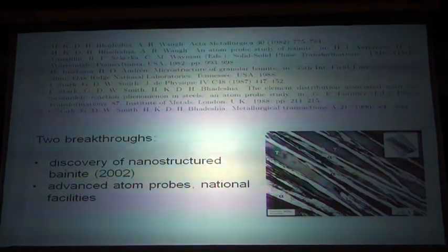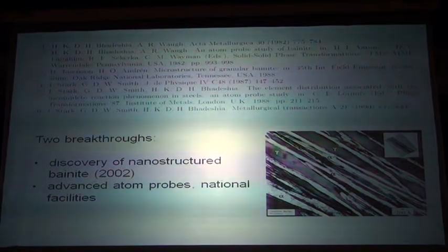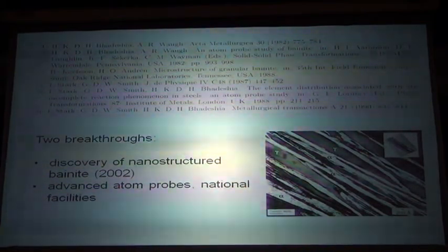When we published that paper, there were several others published by other groups using atom probes, which basically confirmed the results. And the explanation that we adopted in our 1981 paper was that the carbon is probably present at defects such as dislocations, because dislocations can trap carbon, and what we are measuring is not the solubility of carbon in ferrite, but the carbon that is trapped at dislocations. However, in 2002, the story began to change.